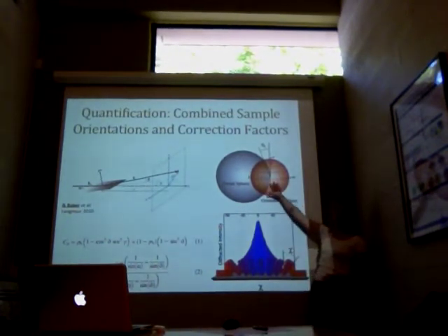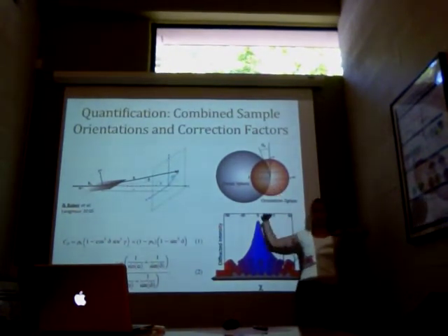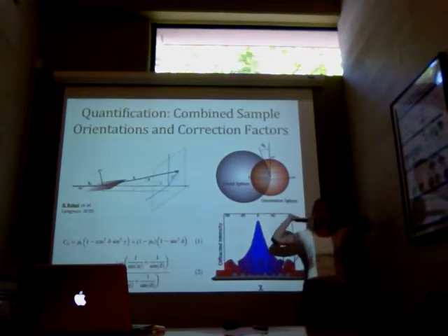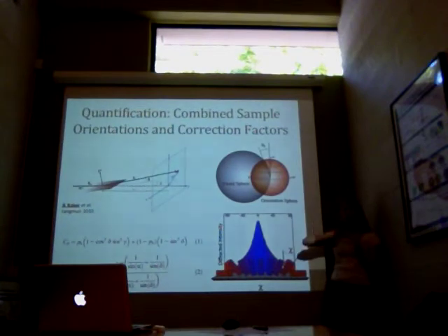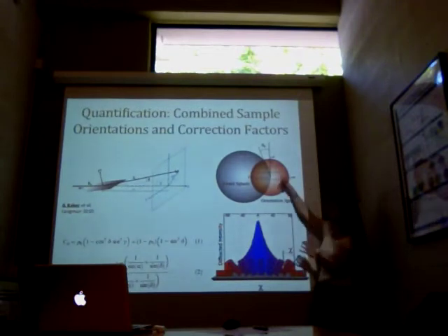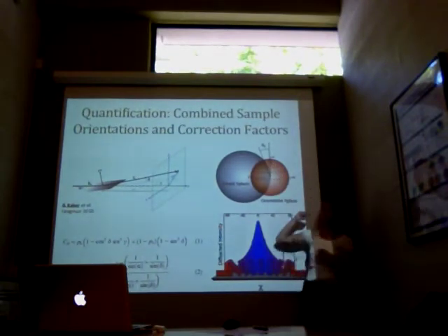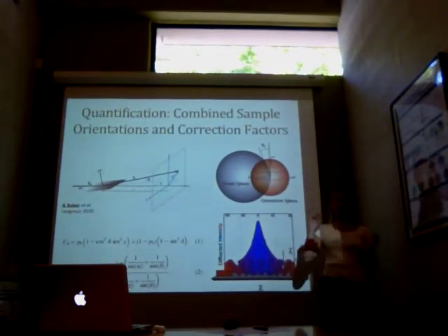So this is in the grazing incidence geometry, and the reason it's grazing incidence is because it's literally coming in almost parallel to the film. But in order to get high resolution of the peak, it's going to show all the nanorods standing up, which we really need. Then we tilt it by this angle, theta d, into the specular condition.